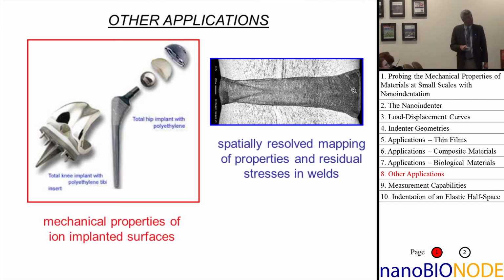Other applications: I put this one in because this is a biomaterial, right? That's a soft biomaterial. The reason that I put this one in is that this is actually what the very first commercial nanoindenter was sold for. It was sold to probe the properties of ion-implanted layers that are put onto hip joints to harden the surface. And this is another good example of the kinds of things that can be done. The ion-implanted layers are only a micron thick or so, and no one had any idea how much that was really hardening that surface. And so nanoindentation, being able to do this at 100 nanometers or 10 nanometers or so, the first commercial nanoindenter was sold to a company that was interested in trying to determine what the hardness of the surface layer was on that hip joint.